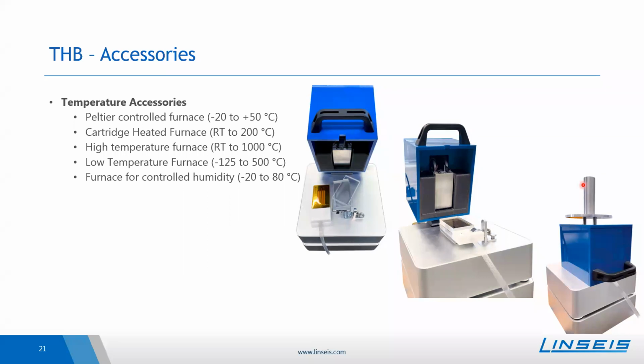To realize temperature dependent measurements of the thermal conductivity, one needs an additional furnace, because the sensor heating is not strong enough to approach, for example, 100 degrees. The sensor heats up the sample only locally and by a few Kelvin, typically in the range of 1 to 4 Kelvin. So you cannot realize temperature dependent measurements just with the sensor, and one needs an additional furnace for this kind of application.